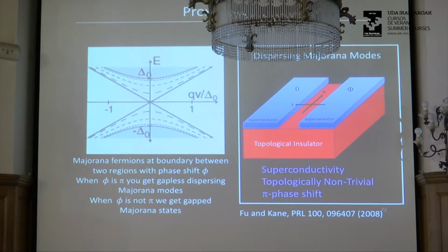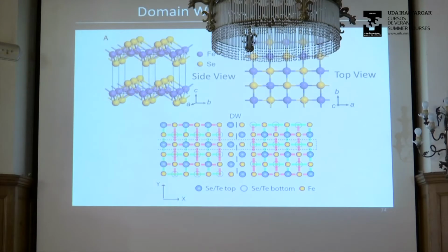So you need superconductivity, and you need something that's topologically non-trivial, and you need a pi phase shift. We have these 2. How do we get a pi phase shift? Okay. Now you can do it by making devices, but that's really difficult. However, there is something that's pretty cool about this compound, and that is that, like I told you before, the crystal structure has this ambiguity. So these are the top seleniums, these are the bottom seleniums. These might have been the bottom, these might have been the top. There is this ambiguity. So when the crystal grows, once in a while, it can flip the top to the bottom. And when that happens, you'll get a domain wall, right?